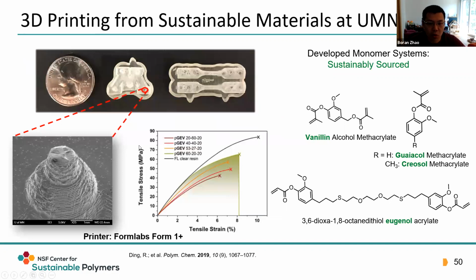Here is an example of work done at UMN by Professor Rennike's group. In this work, novel acrylate monomers are developed from phenolic alcohols harvested from softwood lignin. They are sustainable, and results shown here demonstrate that they can not only generate successful SLA prints, but the thermal and mechanical properties of these prints are also comparable with commercial SLA resins, for example from Formlabs.